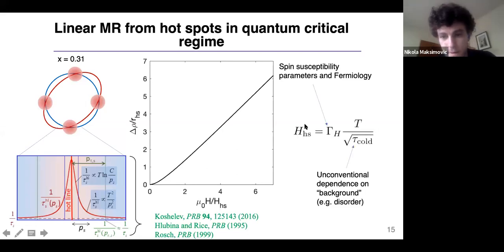So here I show what this magnetoresistance parameter is, what it looks like. There's this coefficient, which is a very complicated function of spin susceptibility parameters in fermiology. It's very difficult for us to calculate this and compare to experimental data because there's a lot of unknowns here. One of the things we can compare is the dependence of these parameters on the background scattering rate.